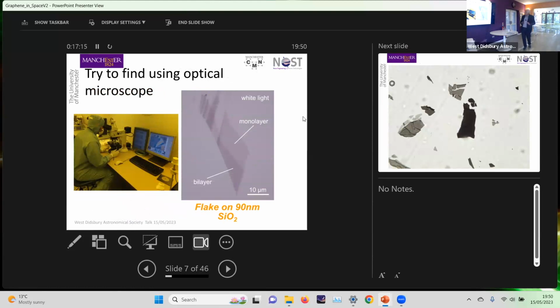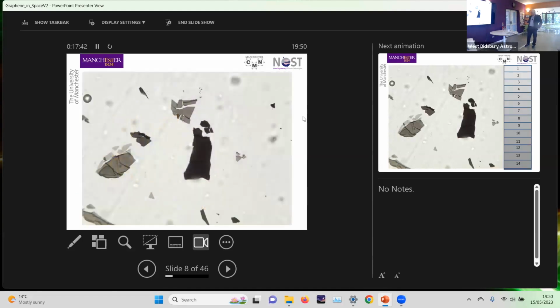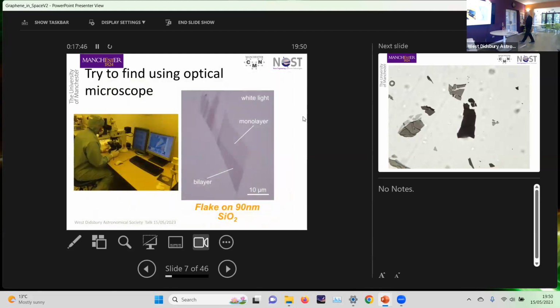Okay, but Kostya, being Kostya, managed to actually show that what you could do is put it onto silicon. In fact, it's actually on silicon dioxide, because the silicon is covered with a thin oxide layer. Most silicon is. And if we put it onto that surface, then you'll find some flakes that look like that. And you can see there, I've indicated a kind of monolayer, which is by eye now. This is what we got used to looking at. When we've done all the measurements, we found that particular level of contrast was a single layer. We never saw anything lighter than that, only darker. And so that's a single layer.